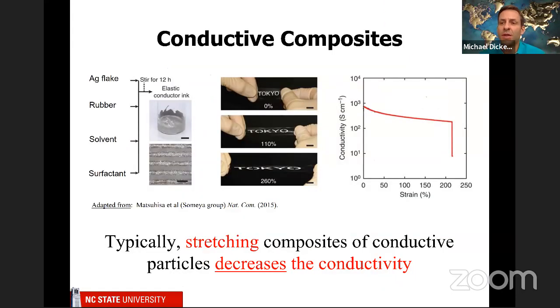To help you understand why this is so unusual, this is some really nice work out of the Someya group in Japan, where they took silver flake. This is a very common material to use in stretchable conductors, mixed it with rubber and solvent, and they made this nice ink, and you can see that it's stretchable. But when you measure the conductivity, you can find that as you stretch it, the conductivity decreases and eventually it breaks and fails. So I'm emphasizing here, typically when you stretch a material or deform it, you decrease the conductivity.